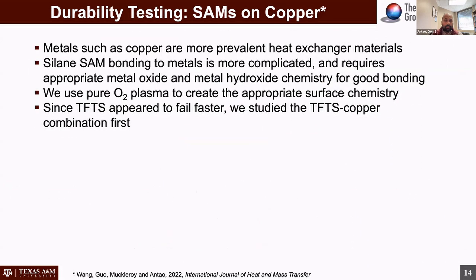The next step was to move to metal oxide surfaces that are more common in heat exchangers. And so we picked copper as a starting point. But silane bonding to these metal oxides is a little more complicated. It's not as straightforward as forming that siloxane bond. And so we had to tweak a little bit the surface chemistry.